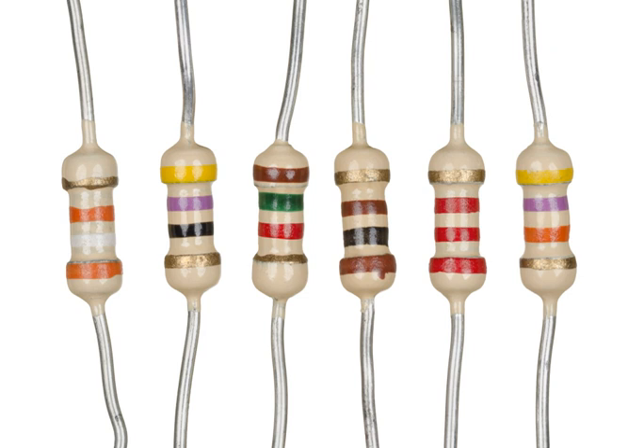long-term stability 1 year 25 ppm, 3 years 50 ppm, further improved five-fold by hermetic sealing, stability under load 2000 hours 0.03%, thermal EMF 0.1 microvolts per degree Celsius, noise minus 42 decibels, voltage coefficient 0.1 ppm/V, inductance 0.08 microhenries, capacitance 0.5 picofarads. The thermal stability of this type of resistor also has to do with the opposing effects of the metal's electrical resistance increasing with temperature, and being reduced by thermal expansion leading to an increase in thickness of the foil, whose other dimensions are constrained by a ceramic substrate.